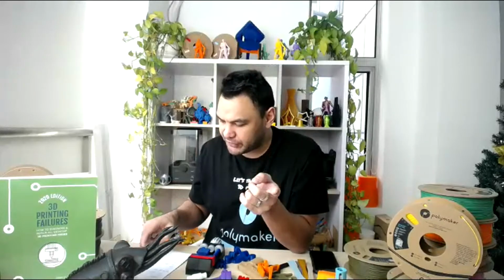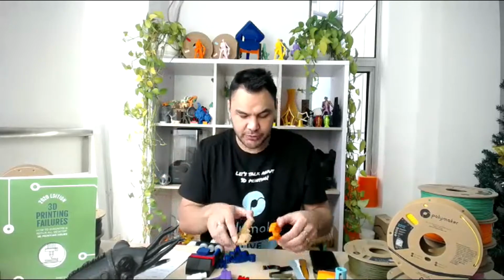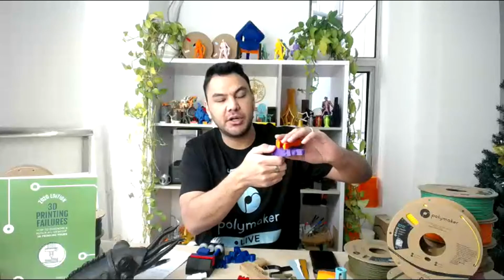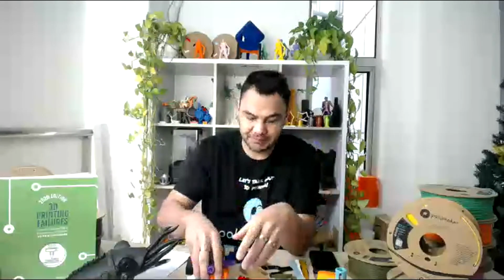multiplier. So the first one was temperature. The second one was pressure. Now the third one is time. We talked about the amount of time it takes for layers to stick to each other, even if it's not above Tg, and the longer, the better. For your print, it's the same. If your two layers can stay in contact with each other at a high enough temperature above Tg for as long as you can, then you will have a much higher layer adhesion.